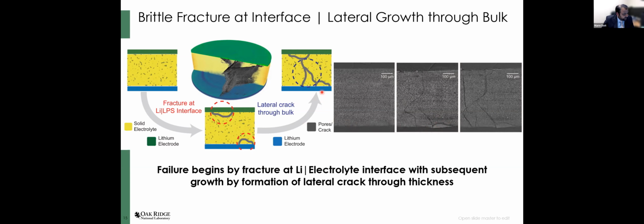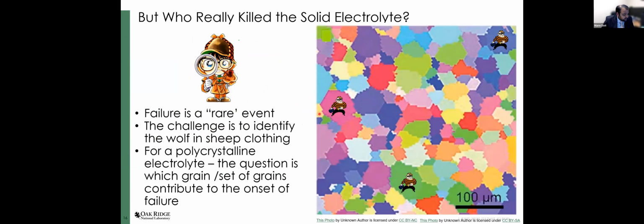And so with these imaging techniques in the first half of my PhD, we were really able to show how filaments form and how these solid electrolytes fail. However, the question that still remains is why these solid electrolytes fail. What is interesting is that failure is a rare event, and it is very challenging to identify exactly what is causing this failure. So for solid electrolytes that are polycrystalline, the question we wanted to ask was what grain or what set of grains contribute to this onset of failure in these solid electrolytes.